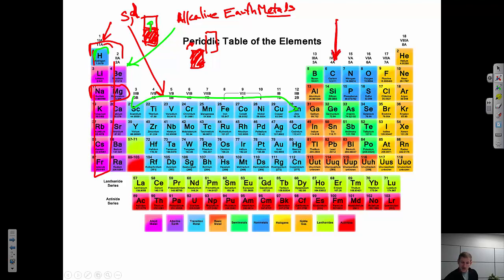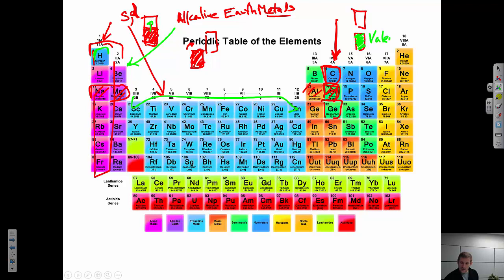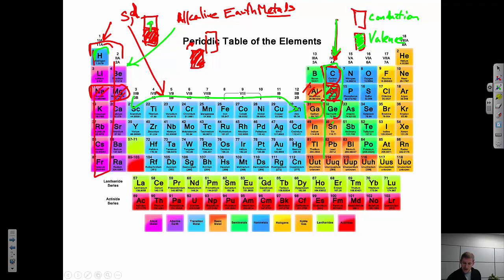If I think about the traditional semiconductors — things like silicon, germanium, and even diamond which is considered a wide bandgap semiconductor — I have a picture that is roughly half full of electrons. Silicon, for example, has four valence electrons, and by the octet rule I would like to have eight for a full closed shell — so that's halfway full. When I look at the band structure, I have exactly enough electrons to fill up the valence band, but not enough to start filling the conduction band. Gallium arsenide, aluminum arsenide, and aluminum phosphide are also semiconductors — they always add up to this half-full picture.